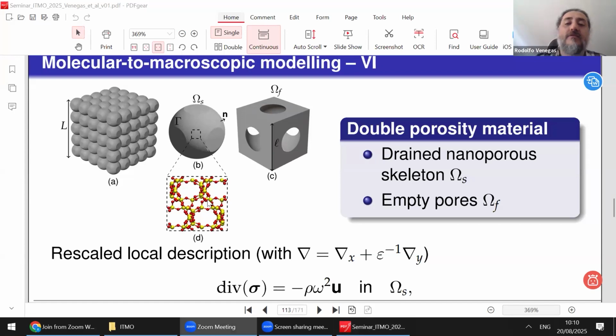But then, as soon as you start scaling this thing up, then we have, for example, defects in fabrication, and that creates microfractures or anything, and that breaks every sort of periodicity and randomness. But the good thing is that it has been shown that, in terms of this macroscopic description, whether you start by assuming that the material is periodic at the local scale or random, you end up with the same type of macroscopic equation.